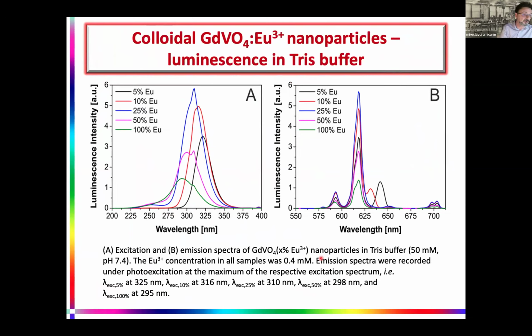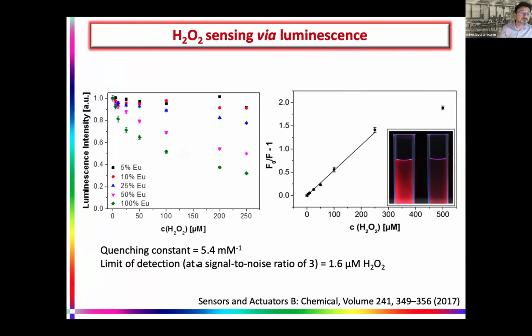I didn't show here the very good quantum efficiency of these nanoparticles, even though they are very small. But what was interesting is that when we introduce hydrogen peroxide inside Tris buffer, so it's a colloidal solution inside Tris buffer, we observed quenching of luminescence intensity depending on the concentration of europium, and for 50% and 100% of doping, this quenching was very strong, and for this best sample, the quenching constant was rather high, and the limit of detection was 1.6 micromolar of hydrogen peroxide.